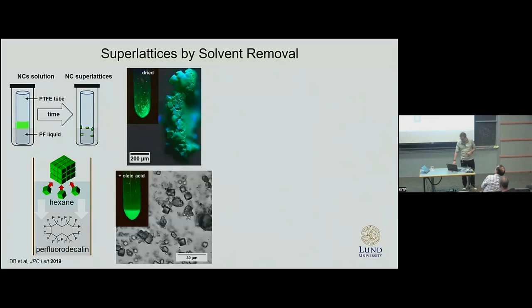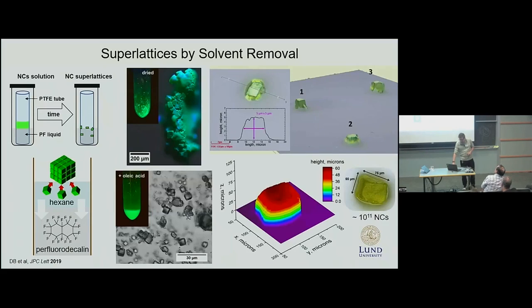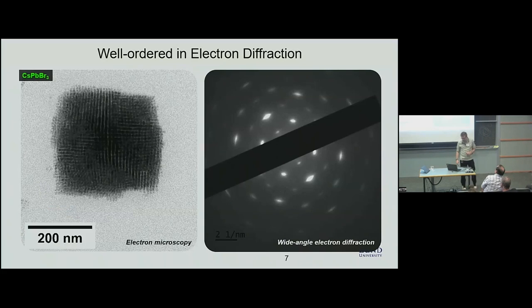These turned out to be superlattices that can be dried in a cluster or further dispersed in another solvent. We looked at their topology to convince ourselves they are three-dimensional objects. By this method we can make quite big superlattices, or big assemblies, with an estimated 10 to the 11 nanocrystals inside. One can also make small ones, like this supercrystal here.